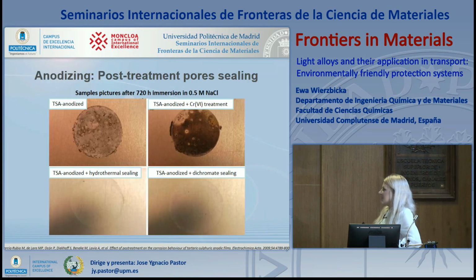The last option is post-treatment pore sealing. As you can see, after very long time exposure to corrosive media, the samples after anodizing and hydrothermal sealing, which is simple hot water treatment, look much better than only anodized samples or even anodized with some chromium-6 post-treatment.